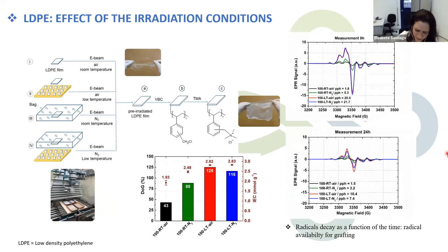So another polymer that we have used a lot is the polyethylene family. So here I'm going to show you some results involving a low density polyethylene. The first challenge was grafting this polymer. It's not easy. When you try under common conditions, I mean room temperature, in air, etc., you have no grafting in this kind of polymer. So you try different radiation conditions to achieve this grafting. So we tried air, nitrogen, and low and room temperature.